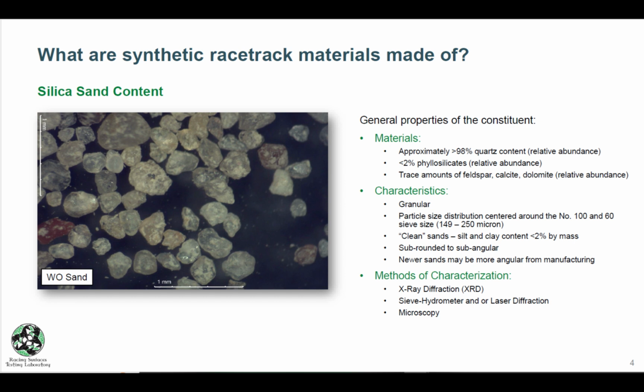And we're looking at the hardness of these minerals, so quartz as opposed to feldspar. It is going to be a narrow particle size distribution. That means you're going to have a lot of sand of the same size. We can test these with X-ray diffraction, that's how we know the quartz content. Of course, we do particle size distribution, so we know how big the sand is. And then we look at microscopy so we can make sure that it's not going to be too angular or too rounded.